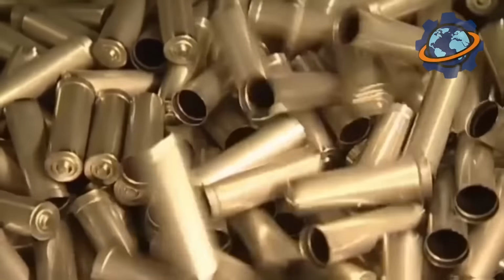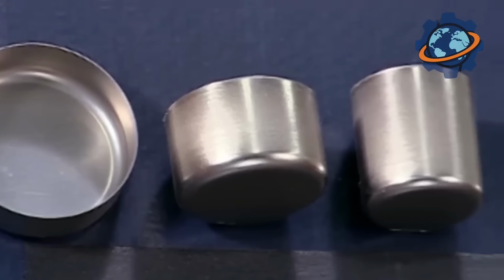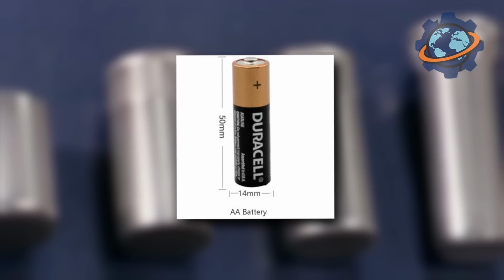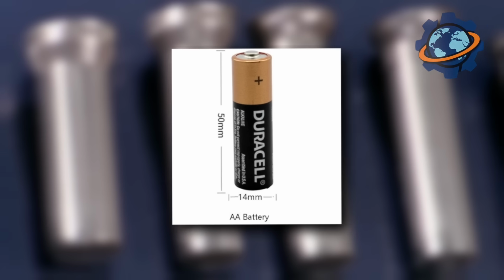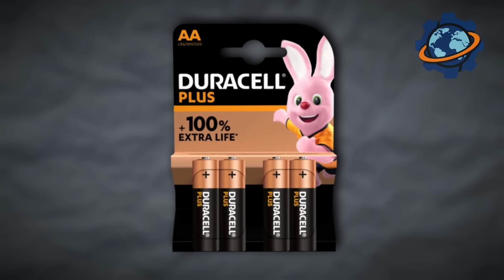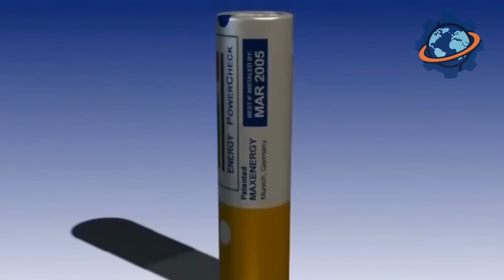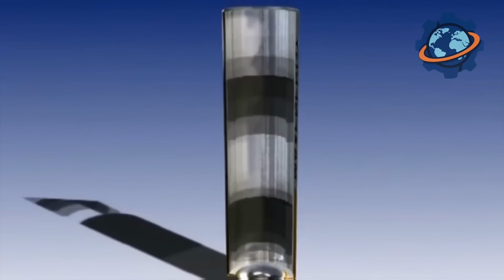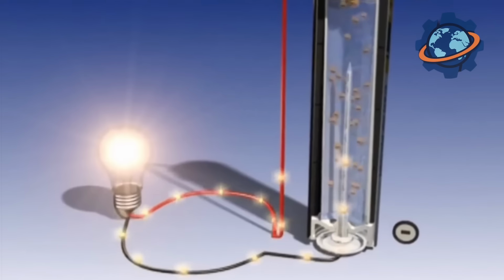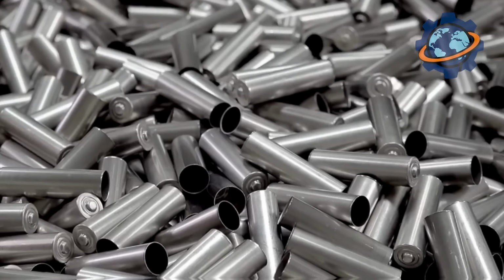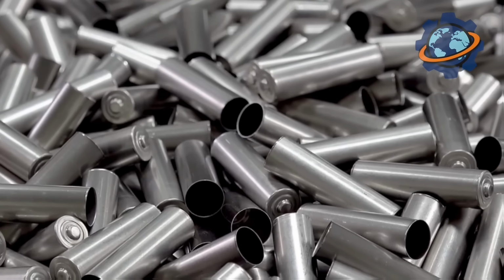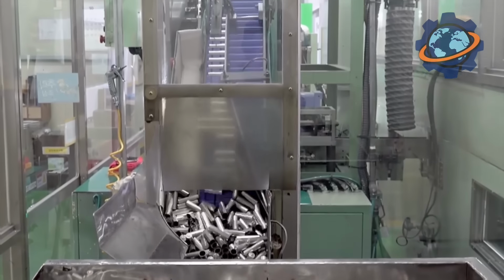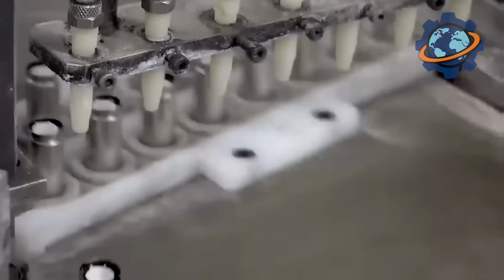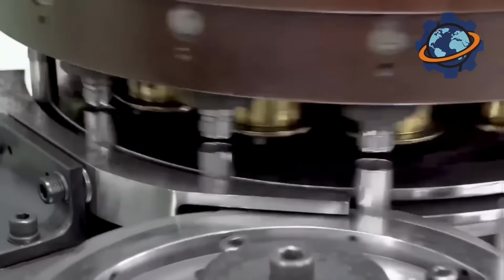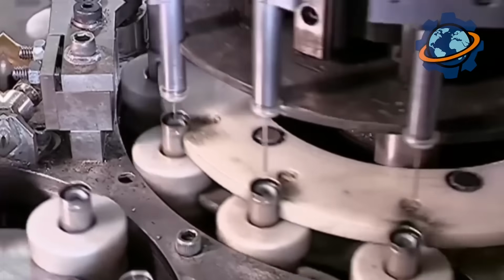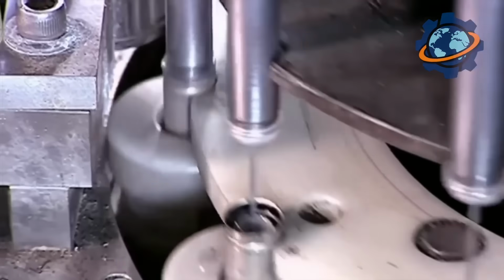Not with energy, not with electricity, but with a small steel can, about 2 inches tall and about half an inch in diameter if we're talking about a classic AA battery. This cylinder is not just a shell, it's the cathode, the positive electrode that holds all the power inside. The production begins with hundreds of these cans, one after another, racing down a conveyor. First, a paste of manganese dioxide mixed with graphite is pressed into the can under pressure. This mixture is the heart of the cathode.